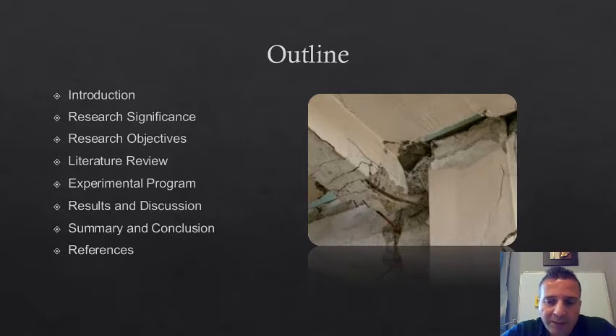Here we want to study the effect on enhancing the strength of RC beams. The unanchored specimen failed by debonding of the sheets. In order to prevent that failure mode and to enhance the performance of the beam further, we anchored the ends with U-wraps. Another possibility is, with the same amount of area that we used to anchor the ends, to anchor at intermediate intervals along the span of the beam.